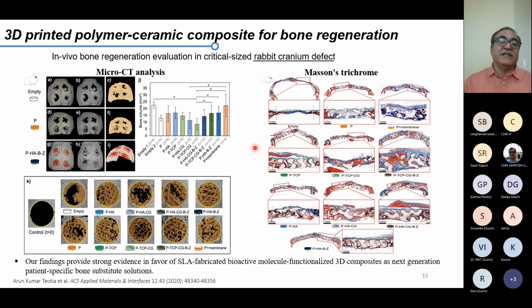The other was on the rabbit cranial part, where you can have 4 defects created. You have the empty defect, then you have PTMC, and then you have PTMC hydroxyapatite with both bioactive molecules. Again, a different number of groups are there, but I'm just showing the outcome of just 2 groups. But we also varied here the calcium salt, hydroxyapatite, and in another case we added tricalcium phosphate. Both of these are typically used in bone regeneration, but in various combinations. Again, I'm not going into detail with the histology part, but in the case of the group having both BMP and ZA, you got a recovery within a period of 4 months. In the others, the recovery was there as compared to just the sham, but still the recovery was not as fast as in the case of BMP and ZA.